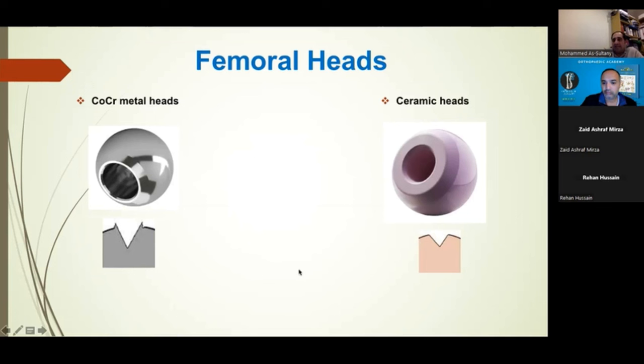The other thing I've added here, some of you may or may not be aware of, is the scratch profile. When you scratch a metal, you get this V shape. You also get these little spikes in the surface, and that roughens the surface as a result. That could then increase the roughness and possible wear of the softer material, which in most cases would be the poly. However, with a ceramic scratch, you get a smoother and not such a rough, peaky outline. So the scratch profile of a ceramic is much better than that of a metal head.